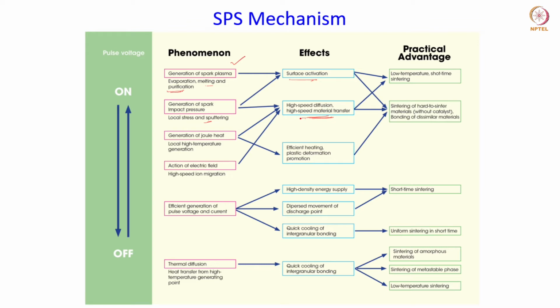Then this sparking leads to the Joule heating, as we have discussed, and that leads to local high temperature, and the effect of that is efficient heating and plastic deformation when the pressure is applied. So all these phenomena and their effects are actually interrelated, as you could see from these arrows. So Joule heating not only leads to efficient heating, but it also contributes to high speed diffusion. Similarly, the spark generation contributes to high speed diffusion as well as the surface activation process also, right?